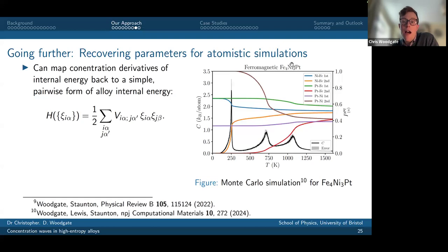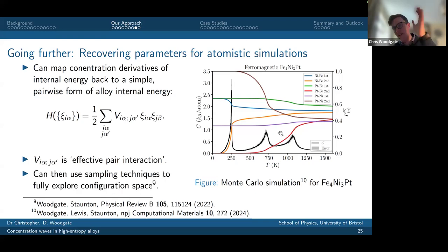And so this is an example of an iron nickel platinum alloy that we studied. The Landau theory would give you the initial ordering at just over 1000 Kelvin. But by doing some kind of Monte Carlo simulation or using these effective pair interactions, I can see that there are subsequent additional orderings with reducing temperature. Vi alpha is this effective pair interaction, and we can use various sampling techniques to explore the phase space. Okay, good.